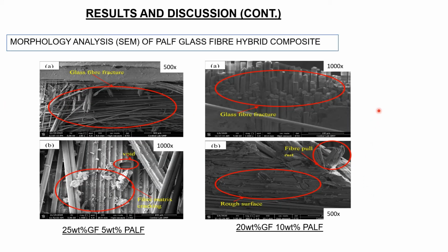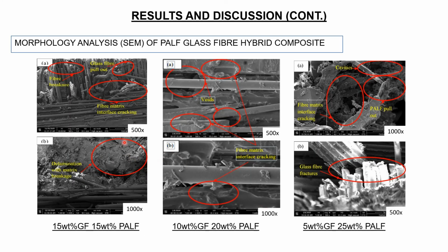Here are the results for morphology analysis. As we can see, at 5% PALF, there was a lot of glass fiber fracture and some voids and fiber matrix cracking. Meanwhile, at 10% of PALF, there was glass fiber fracture, fiber pull out, and rough surface. At 15% of PALF, there were glass fiber pull out, fiber matrix interface cracking, fiber breakage, and delamination with matrix breakage. At 20%, there were a lot of voids and fiber matrix interface cracking.